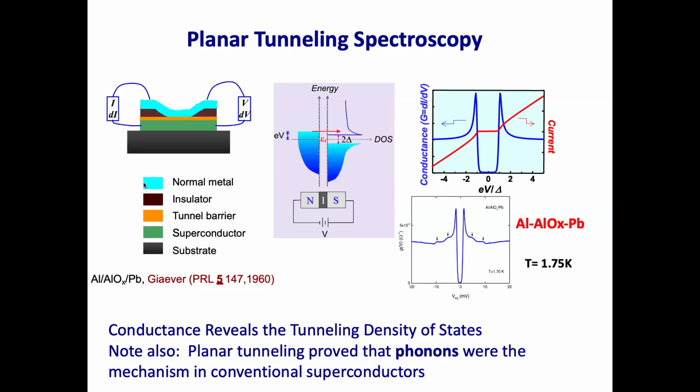So that could be any simple S-wave superconductor where, at zero bias, we don't have any electrons get across because everything's paired. And that's going to happen until you get to the gap edge. And then Mr. Fermi told us that you have a peak in the density of states, so all the electrons have a high probability of tunneling through.